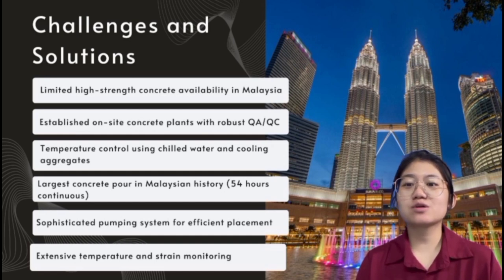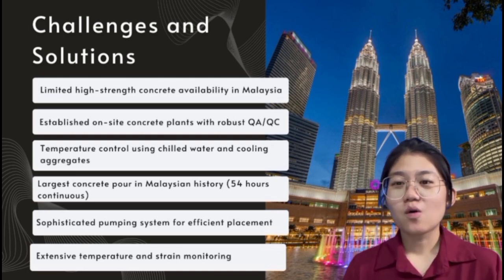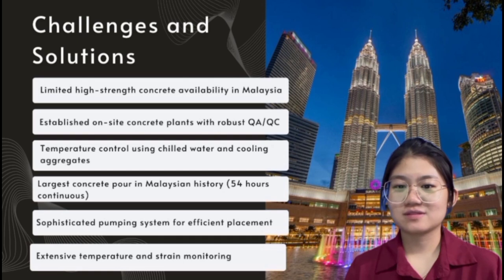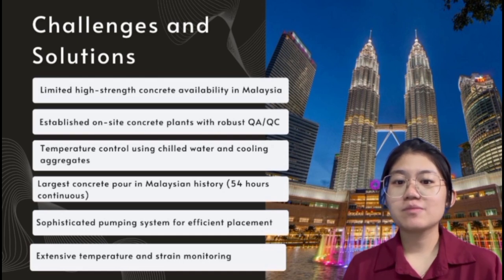Temperature control was also critical. We used chilled water and cooling aggregates to prevent thermal cracking. One of the most remarkable feats was the largest concrete pour in Malaysia's history, spanning 54 hours continuously for each tower. We monitored temperature and strain extensively with 100 gauges on the 6th floor to ensure structural integrity. This strategy and innovative technique were crucial in successfully constructing the Petronas Twin Towers, a symbol of modern engineering excellence.